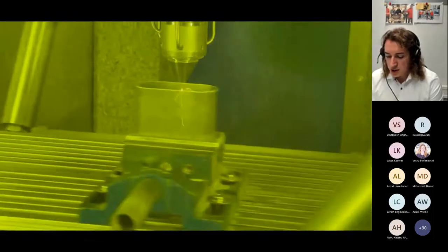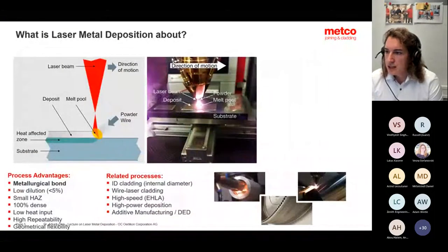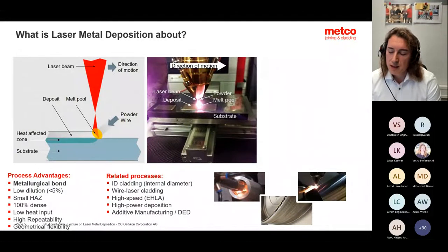An advantage of the technology, which we can also look at on the next slides, is related to the fact that you get metallurgical bonding with a substrate, meaning you don't have any type of adhesion properties in terms of failure. You get low dilution, which is very important in terms of mixing between the substrate material and your coating quality. Typically, we get below 5%. Also, the heat input is quite low, leading to the fact that the heat-affected zone might be quite narrow or completely eliminated, depending on how you work.